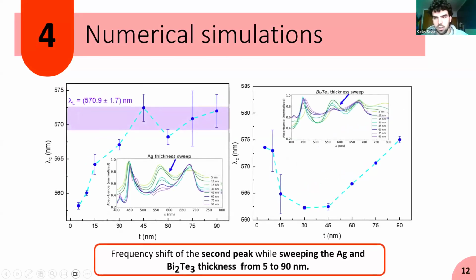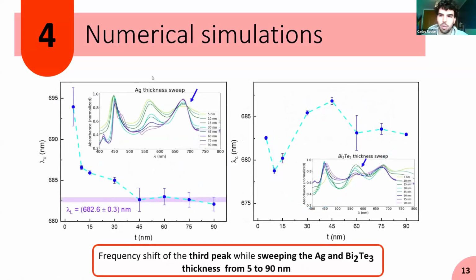And concerning bismuth tellurium, we have different behaviors. And then concerning the third peak, we have the opposite behavior for the silver thickness sweep. The wavelength of excitation decreases with increasing thickness of the silver layer. This matches with the literature reported data for the silver thickness for silver gratings.